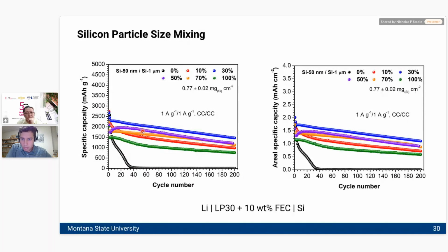50% is purple, 70% is orange, and this green line represents the 100% nano system. So there's a real synergistic effect here: if you mix these two materials together, it doesn't just give you a linear combination of the effects of the nano plus the micron, because then you would expect everything here to fall in between these two cases. Instead, there's actually a significant improvement to be had by mixing the two together.